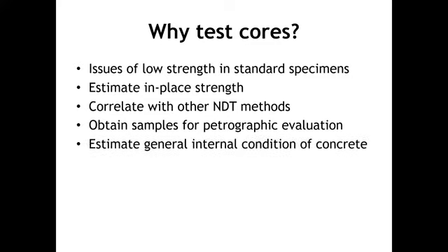17.4.3. As we take it as a cylinder, whatever the FCM value you get, you can multiply it by 1.25 to get your equivalent cube strength after applying your correction factor. Also, SP 24 says, if the diameter of the core is less than 100 millimeter, you can add 8% strength to whatever you obtain from the core, maybe 69 millimeter diameter or so. So these are all the acceptance criteria when you go for it.